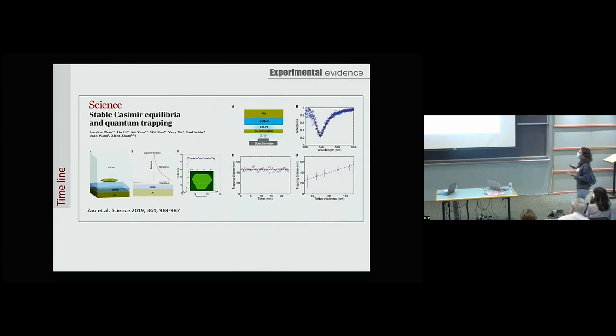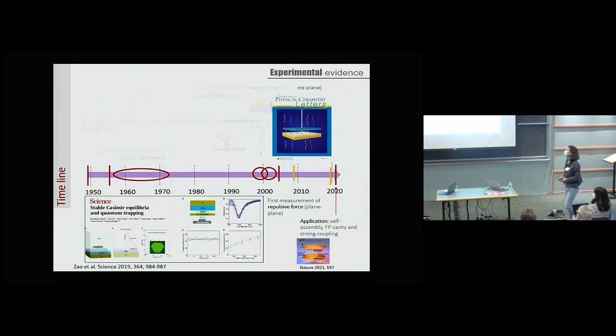So the difference between them is, first of all, these are micrometer scale, the flake. There is ethanol that we did not consider because of the evaporation problems. They considered also Teflon that we also discarded because of the electrostatic force and the carboxyl groups that can be transferred and so on. But it just worked out very well.